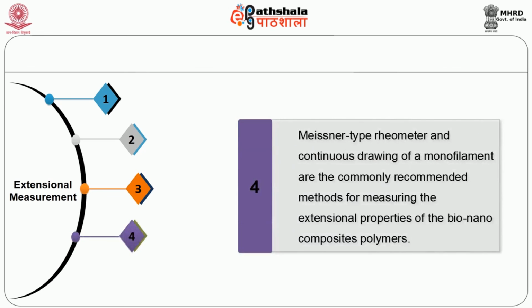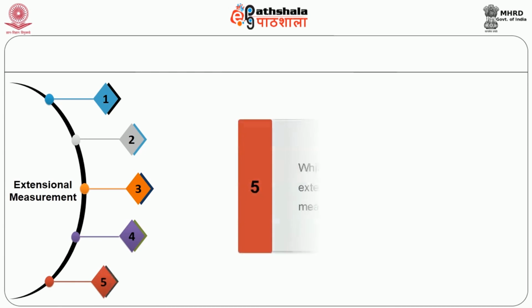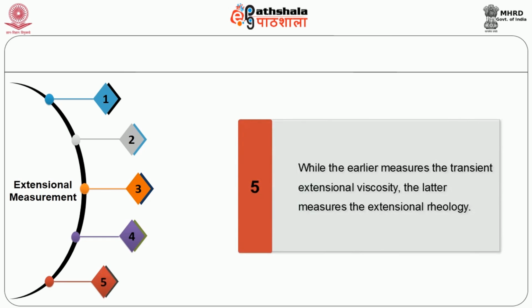Meissner type rheometer and continuous drawing of a monofilament are the commonly recommended methods for measuring the extensional properties of the bio-nanocomposite polymers. While the former measures the transient extensional viscosity, the latter measures the extensional rheology. After a very long discussion on testing of bio-nano packaging material, I would like to conclude that the environmental pollution caused by the use of synthetic packaging material has reached a dangerous position, particularly in developing countries. This could be mitigated by the use of